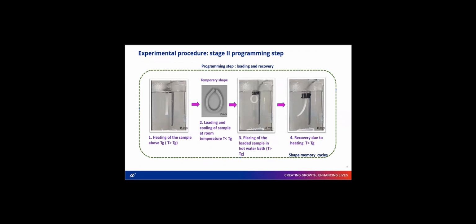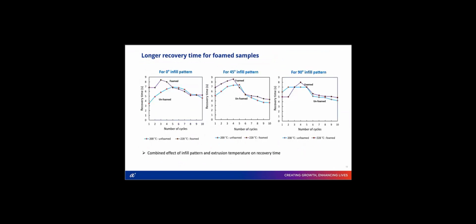for each sample. The average recovery time for each sample printed at different infill pattern and extrusion temperature is plotted here. From this, we can see a pattern: there is a decrease in the recovery time for both the foamed and unfoamed samples, and there is a longer recovery time for the foamed sample. Through this we also concluded that there is a combined effect of infill pattern and extrusion temperature on the recovery time.